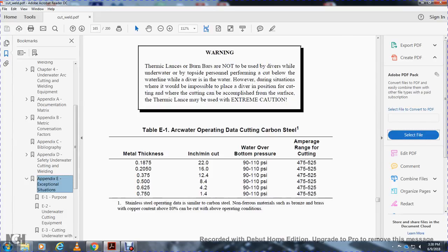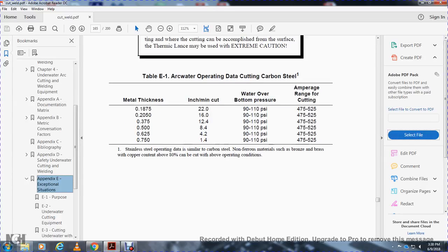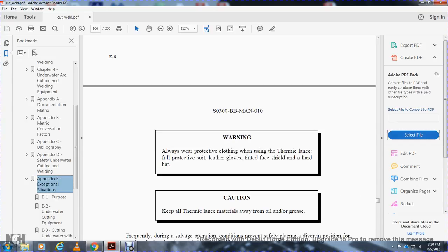Table E1, operating data for cutting carbon steel. Metal thickness in inches, inches per minute, and cut. Water over bottom pressure would be 90 to 110 psi, and the amperage range for cutting is from 475 to 525. Stainless steel operating data is similar to carbon steel. Non-ferrous metals such as bronze and brass with copper content above 80% can be cut under the above operating conditions.